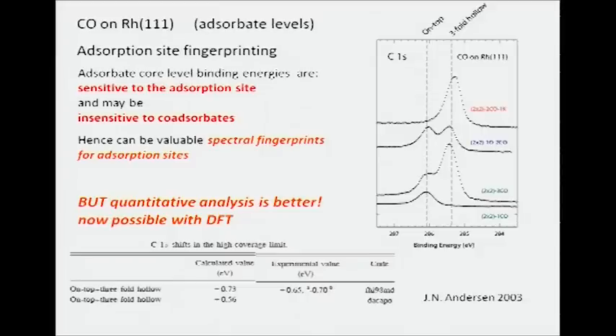And so here in this paper of Jesper Andersen's, they have actually done this, and you see that they've played around with a couple of different standard DFT codes, but you get calculated values for the difference that you expect for these two states, which do correspond pretty well to the experimental values. And indeed,